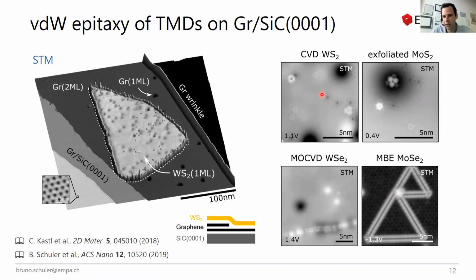So you see also here that we looked into different types of growth methods, so with CVD, MOCVD, and MBE, but also exfoliated samples. So we figured out how to make them clean enough that we can look at them and really fulfill the high surface cleanliness requirements of a scanning probe, even though these materials, of course, were transported through air and everything. So I think this has been a very important step.